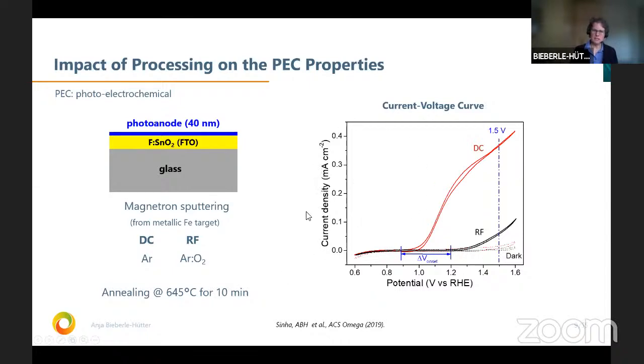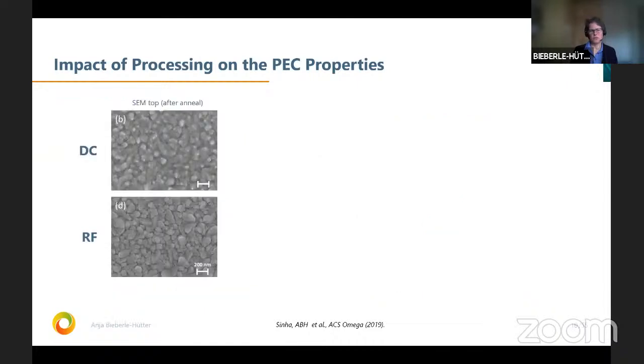Here on the right side, you see now current density over the potential. We see that we have quite a difference in the performance. DC is more like what a lot of people see, RF is a pretty low performance. So we would like to know why it is so different. We get a shift in the onset potential, which is usually related to surface chemistry and catalysis, and the other difference is due to the morphology.